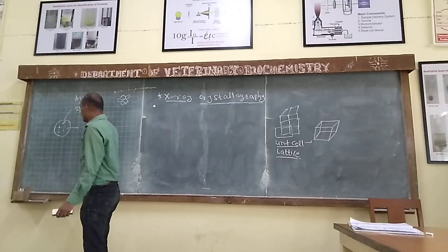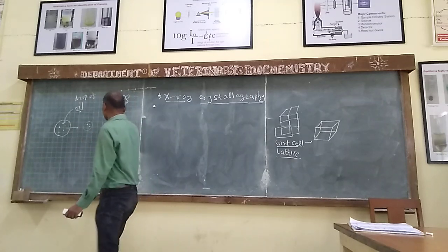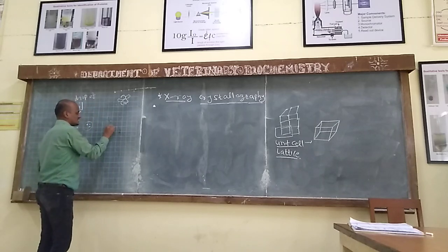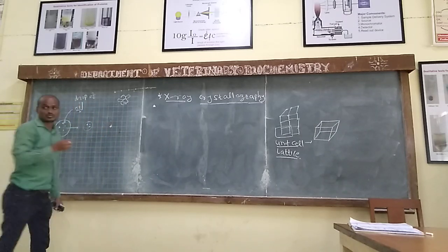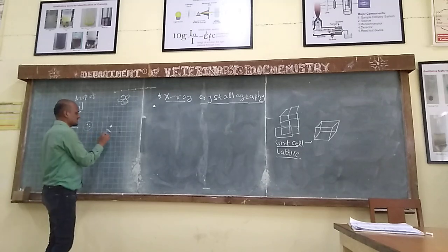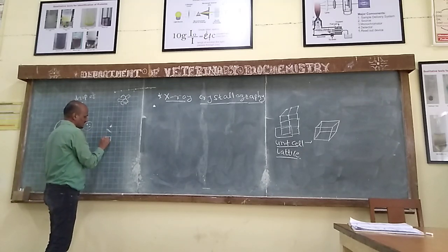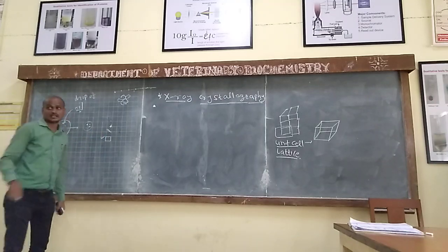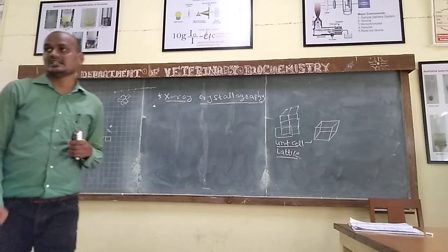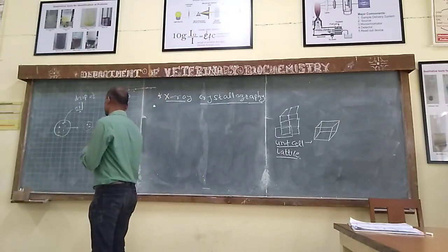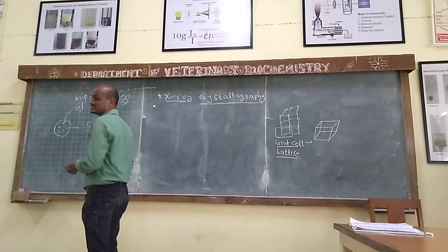Now we observe the crystal. It should not be too small. It should not be like 2-3 crystals coming together, multiple crystals together. It should not be cracked. So this is a crystal, but there is a crack somewhere. It should not be there. The crystals we are selecting should have a regular shape and size. Okay. So this crystal we are going to select out of these crystals after crystallization. So we have done crystallization, and then we have to select the crystals like this. Okay. So this is the crystal selection process.